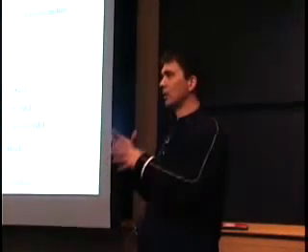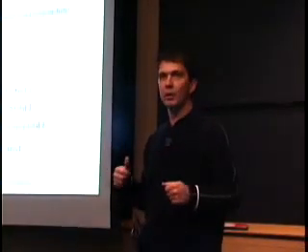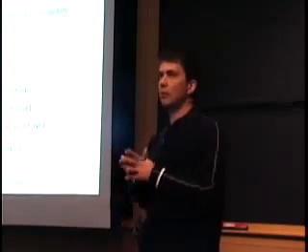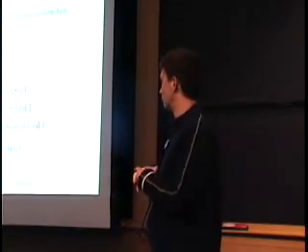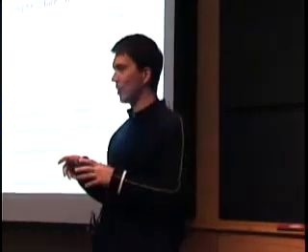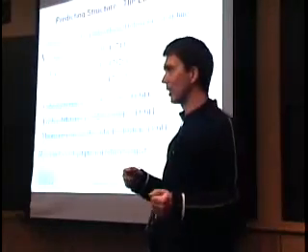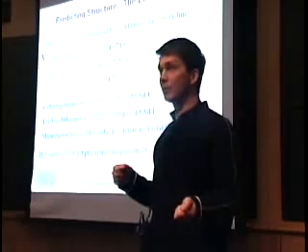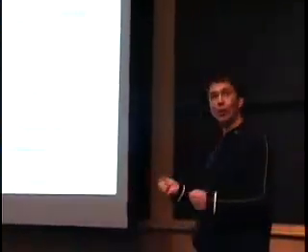If you want to look at mixing energies, let's say I mix vanadium with something else, platinum, and you want to know the mixing enthalpy, because that sets the whole temperature scale for mixing, the whole phase diagram topology. That tends to be a fraction, 10 to the minus 6, 10 to the minus 7, of the total energy. My former advisor used to compare this to wanting to know the weight of a captain that sails a big supertanker. It's like weighing the tanker with the captain and without the captain and looking at the difference. And that's the weight of the captain. You're almost at a relative scale like that here.